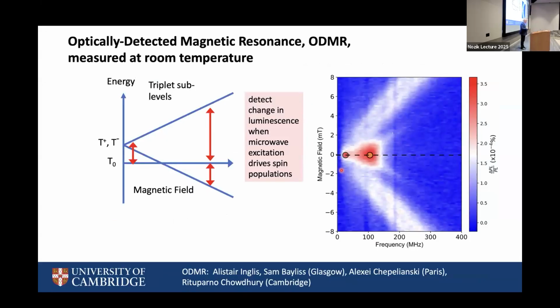We can tell what's happening because it's possible to do electron spin resonance with that at zero field, at room temperature. This is work done with Sam Bayliss at the University of Glasgow, who does wonderful optically detected magnetic resonance measurements. Essentially, we can change the spin populations between the M0 level of the triplet and the plus and minus triplet sublevels. The frequency that couples the two is actually quite low. It's as low as 50 megahertz. And then if you apply a magnetic field, the Zeeman energy will further split the T0 and the T plus and T minus. And as we apply a magnetic field, plus and minus, the resonant frequency follows the trajectory of these white lines. So that's just to show you that we know what is changing with these low fields. So why is that happening?